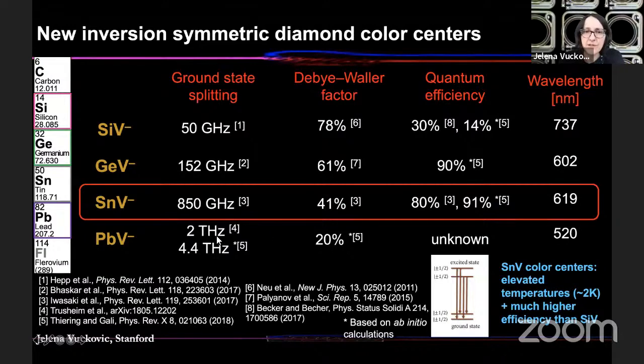And we like tin vacancy because it has a much larger ground state splitting than silicon vacancy. So 850 gigahertz relative to 50 gigahertz, which means that you don't really need to cool the system down to millikelvin temperatures to avoid dephasing and mixing between ground states. For silicon vacancy, all of the state-of-the-art experiments have been done at millikelvin temperatures in dilution refrigerators. But for tin vacancies, we don't need to do that. I can have the system operated at a few Kelvin temperature without a problem.